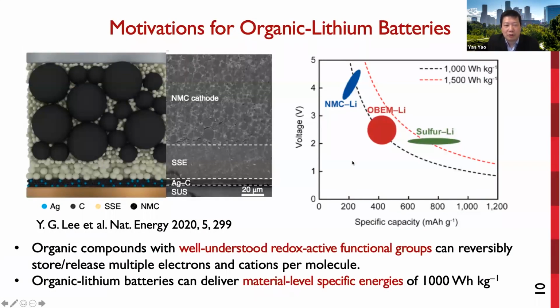The leading cathode material for all solid-state batteries is mainly nickel manganese cobalt oxide, short for NMC. So even if solid-state batteries can work well, the cost of the battery would still be high due to the nickel and cobalt used in these cathodes. To make cobalt-free and nickel-free cathodes and reduce the cost, we propose using organic electrode materials, which are made of carbon, hydrogen, and oxygen, without any transition metals. Organic compounds with well-understood redox-active functional groups can reversibly store and release multiple electrons per molecule.